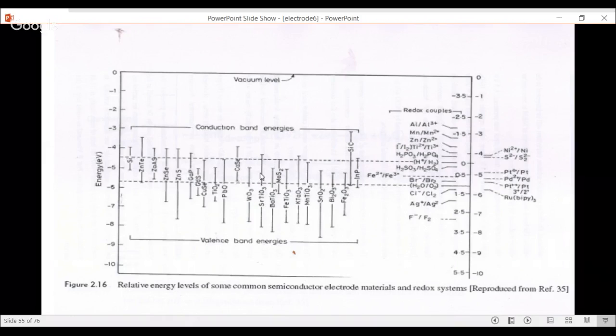I hope you are able to see what is representative here. The conduction band is more negative with respect to hydrogen evolution potential. The valence band is more positive with respect to oxygen evolution potential. There are a few semiconductors shown, for example, silicon. Take silicon: the conduction band edge is more negative with respect to hydrogen evolution potential.